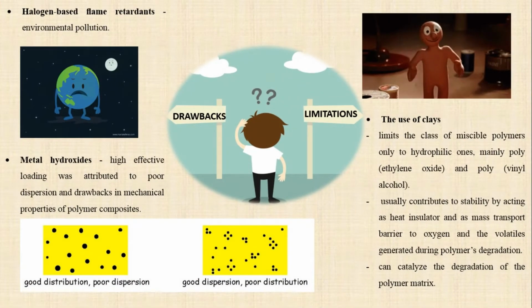Moving on to the drawbacks and limitations, halogen-based flame retardants were used, and these materials were found to be effective for flame retardation. However, these materials were inhibited due to their associated environmental pollution. Other than that, metal hydroxide have been used as flame retardant additives, but their high effective loading was attributed to poor dispersion and drawbacks in mechanical properties of polymer composites.